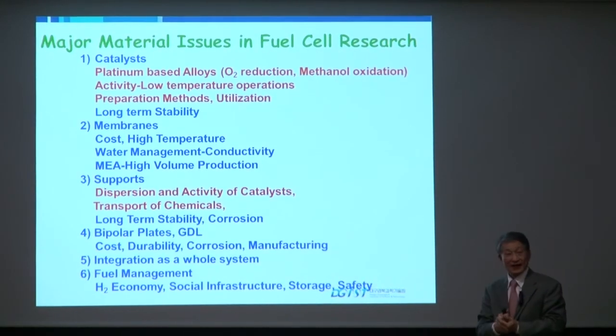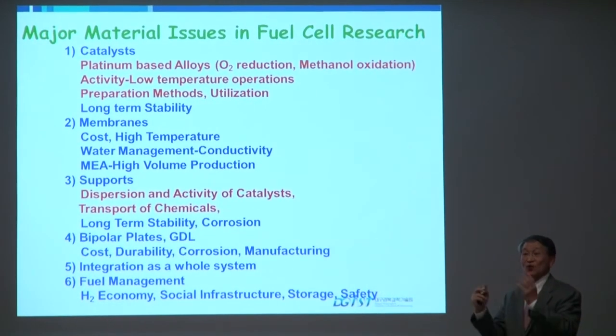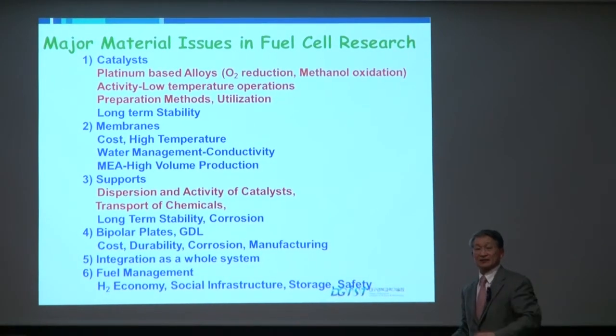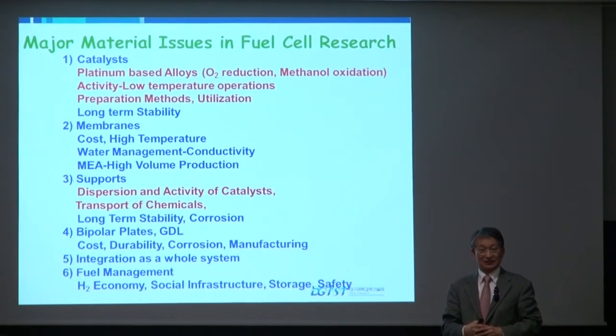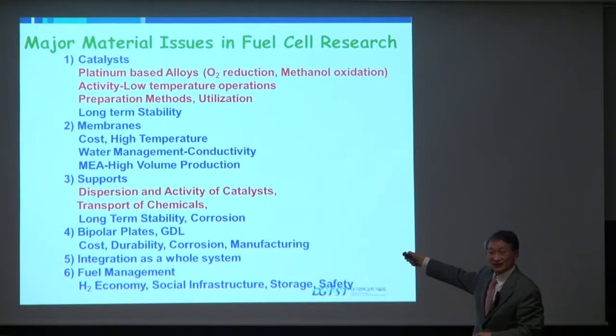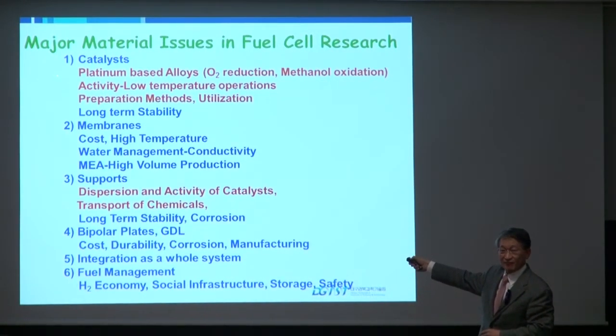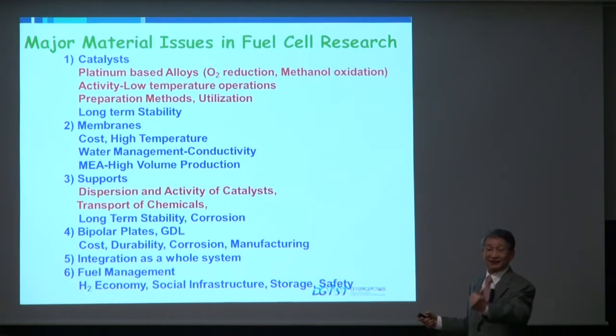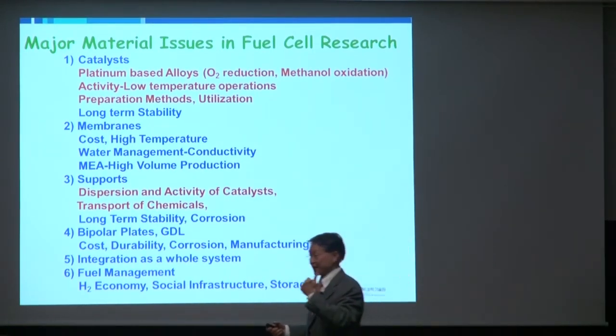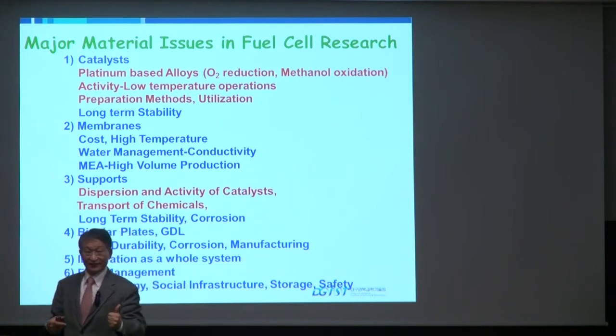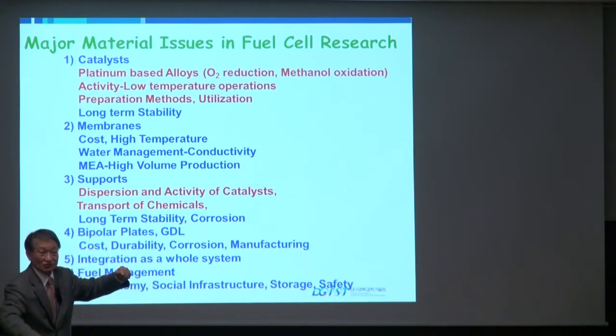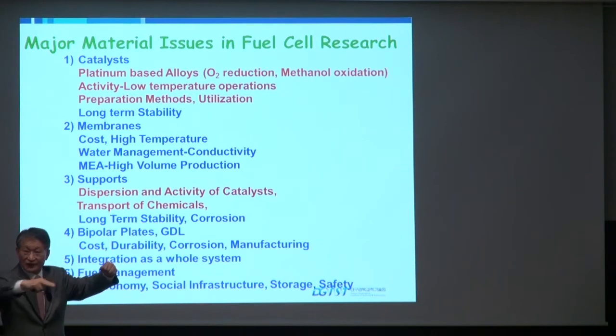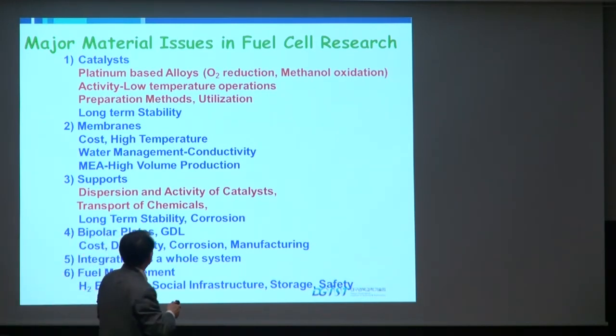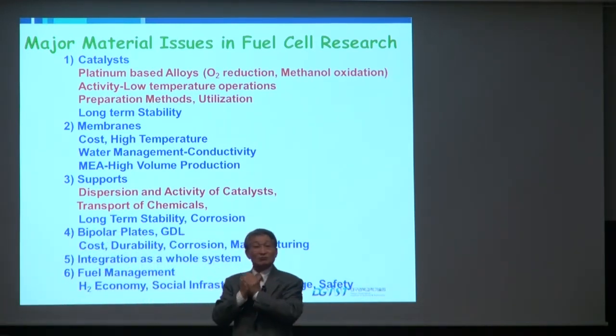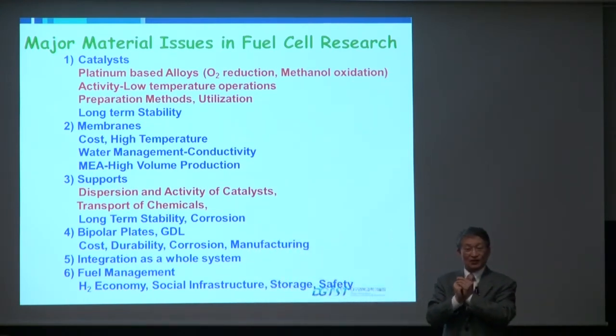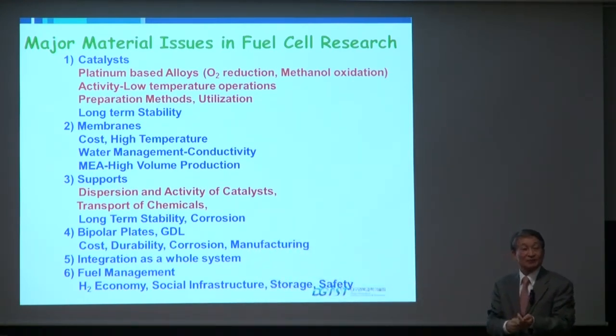Then I'm going to talk about the major issues. It is more like a kinetic part of the problems. The first one, of course, catalyst. You have to have a suitable catalyst which has very low activation energies. When it turned on, it immediately dropped. So we have to have very low overpotentials. But at the moment, platinum is the most popular catalyst, all platinum-containing alloys.